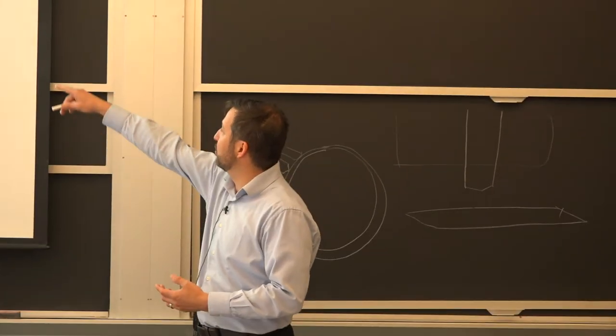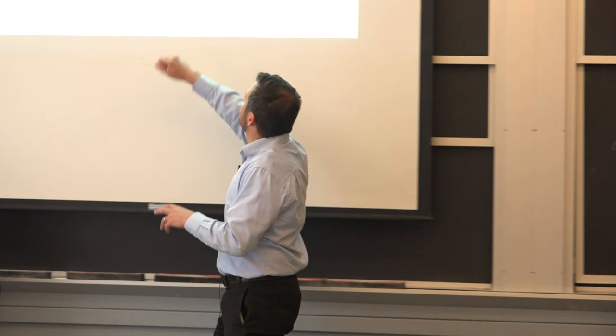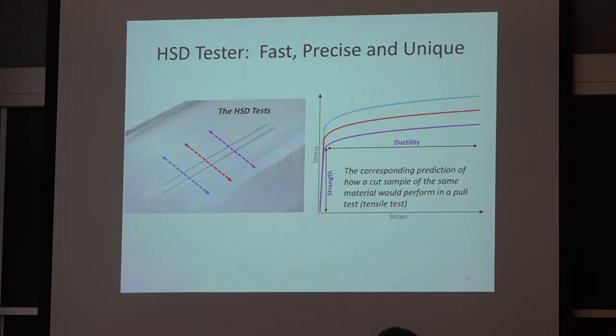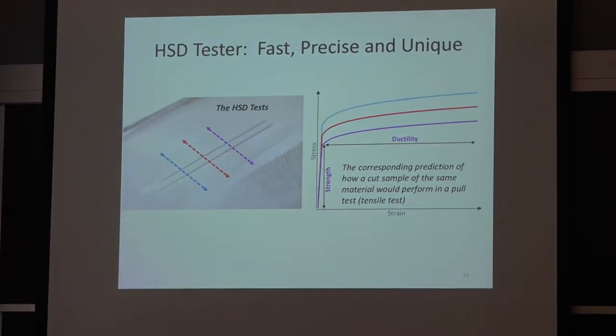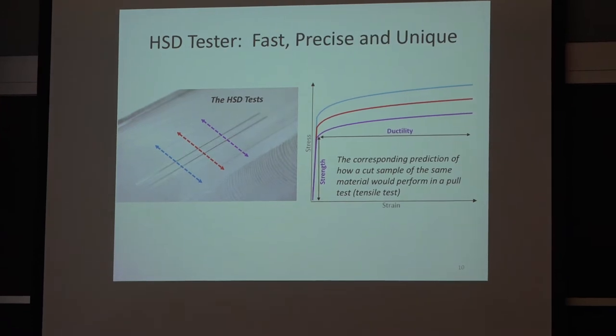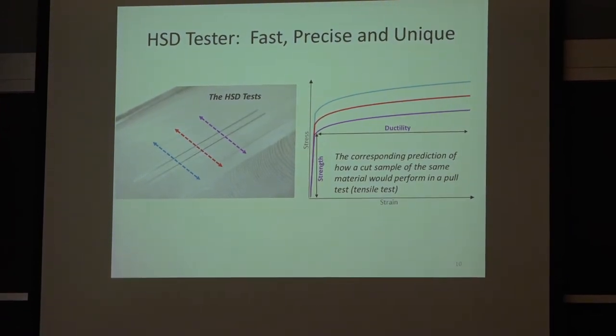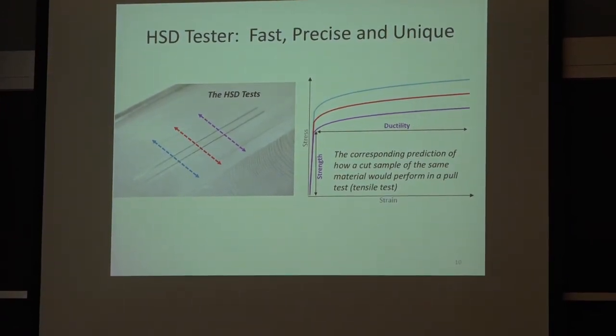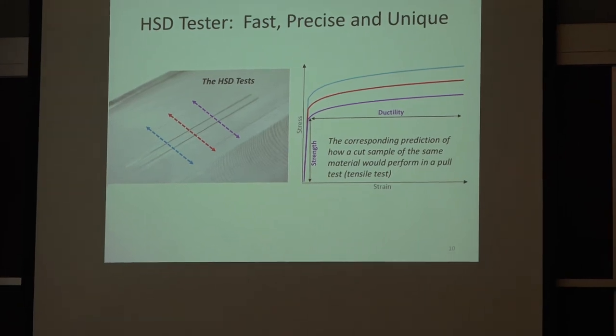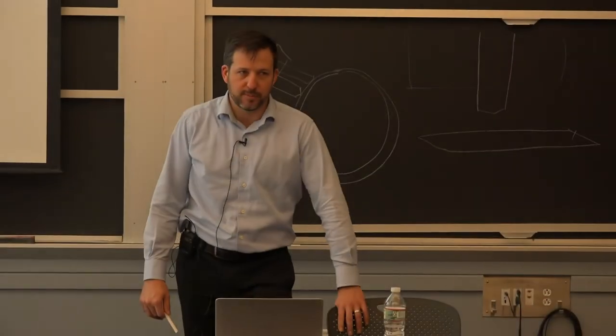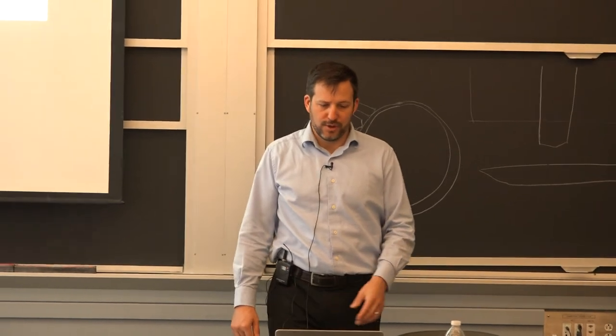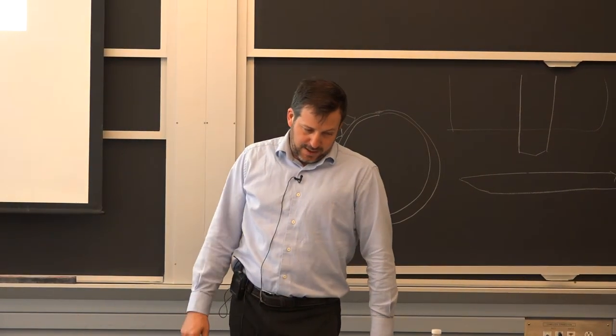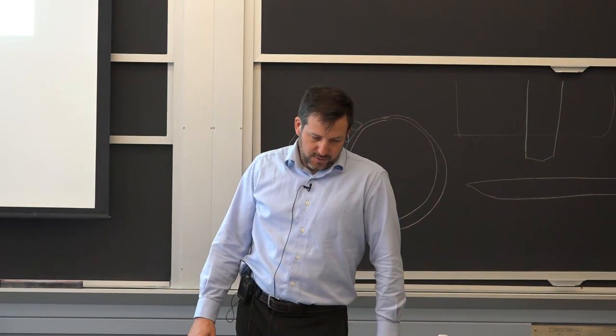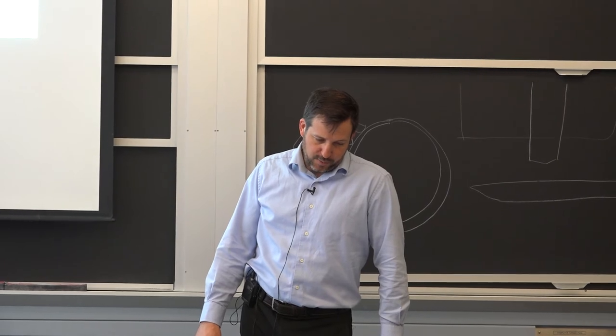So here you get the fingerprint right there in the image. It looks almost as big as the grooves that we're making themselves. And for all you engineers, we go to a depth that is less than 0.5% of the pipe wall thickness. So it doesn't make any difference. We're talking about pipes that have some corrosion, have some anomaly bumps just from the manufacturing. So it wasn't a problem.